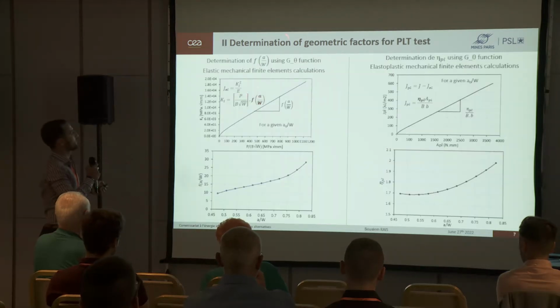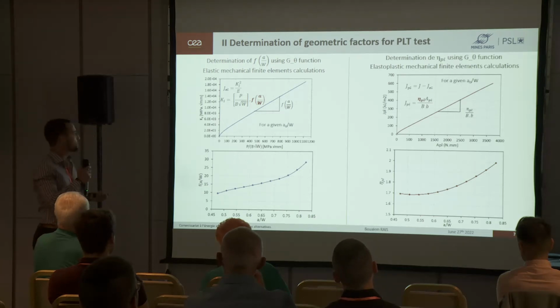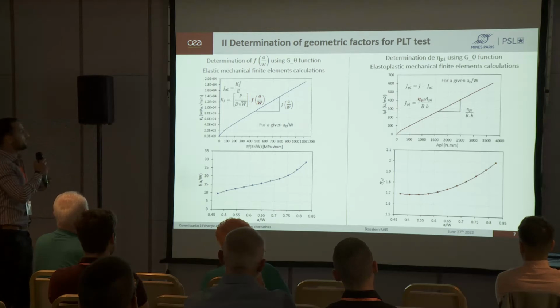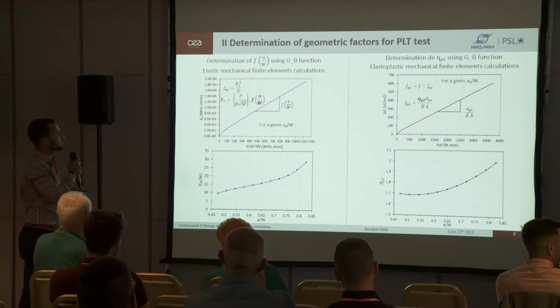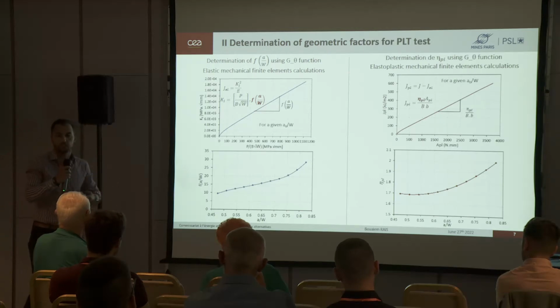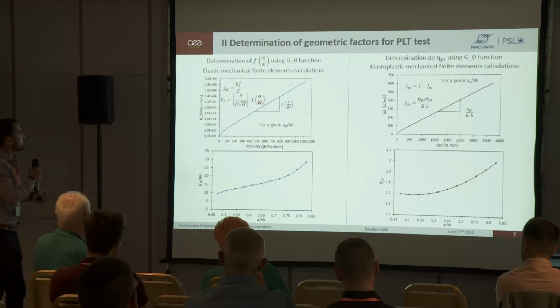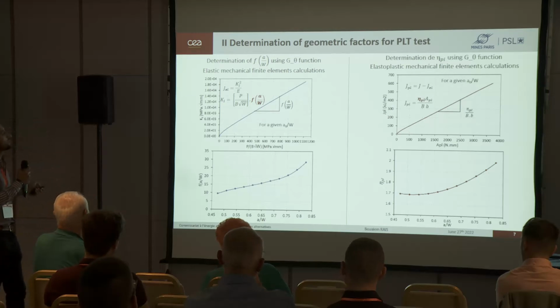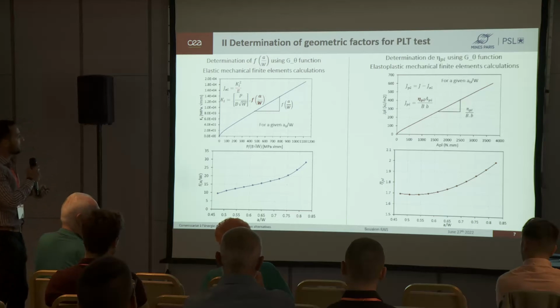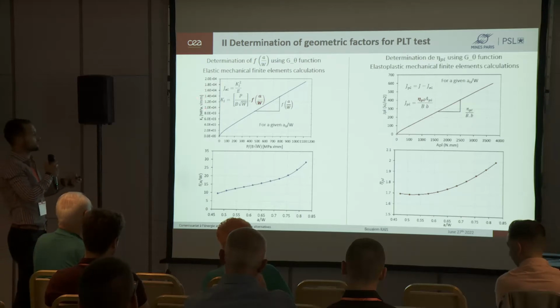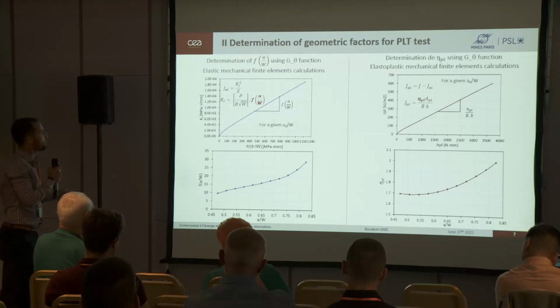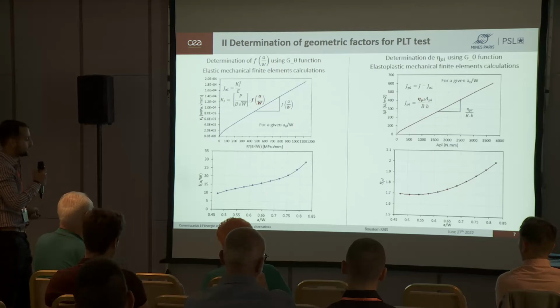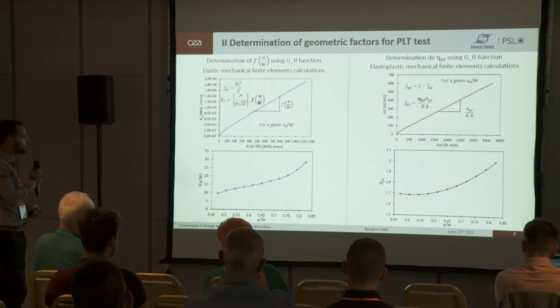First, let's start with the F function, the geometric function F. So we perform some elastic mechanical finite element calculations, then calculate the J integral using the G theta function. It's an implemented function in Castem, the software that I use in my study. So the J integral calculated is purely elastic because we use an elastic mechanical model, and knowing the other parameters, we plot the stress intensity factor as a function of this ratio, and the slope of this curve is our geometric function. So we repeat the exercise for different normalized crack sizes, a divided by W, to have the evolution of the geometric function for these different crack lengths.